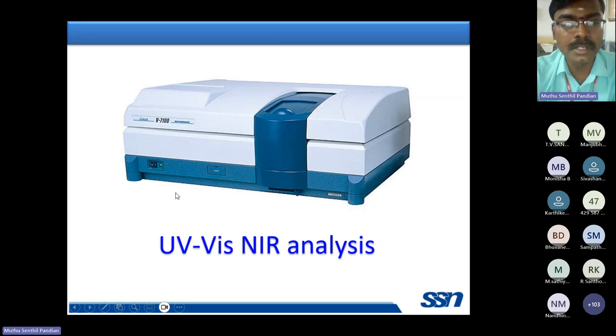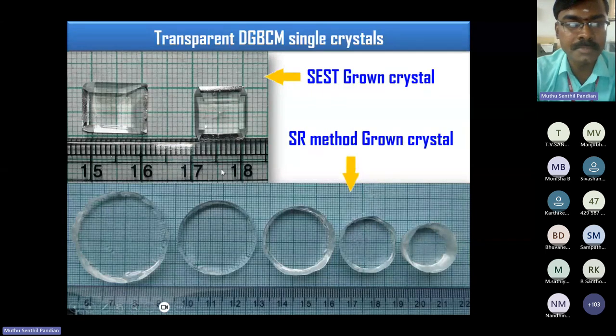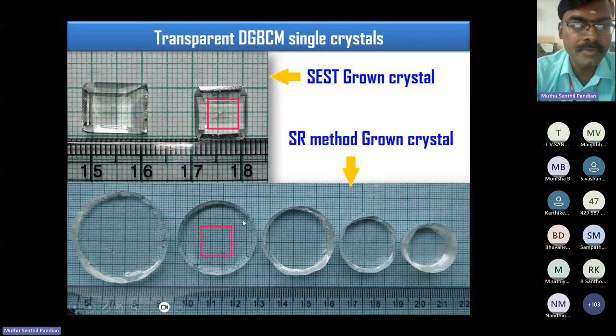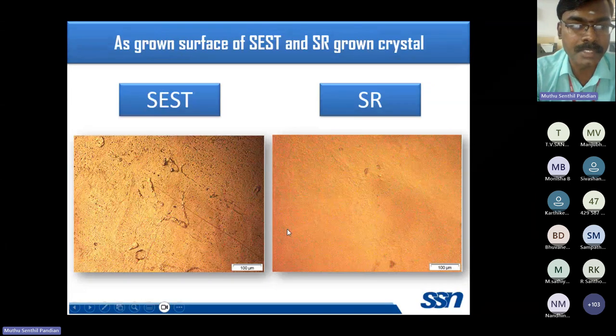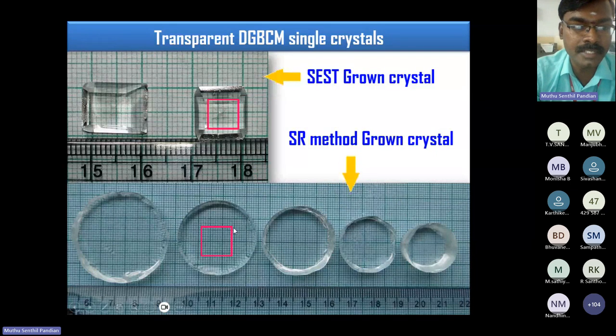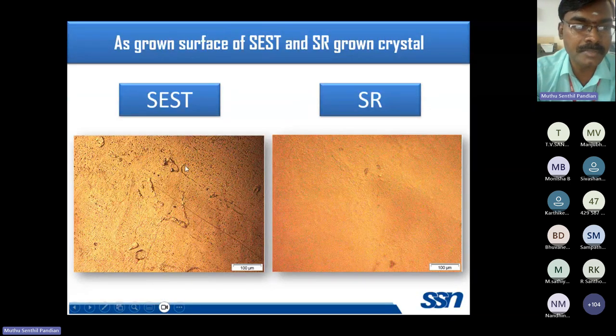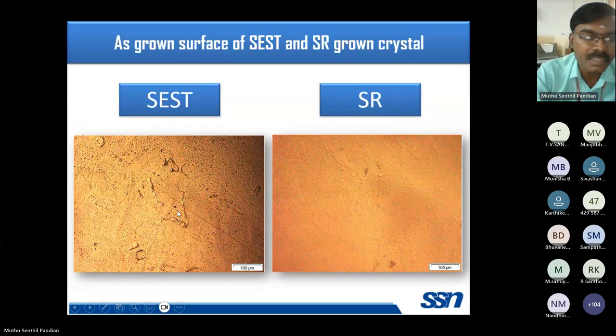To check the optical quality of the conventional and SR method grown crystals, we have performed the UV-Vis measurement. So here, we have performed the optical transmittance measurement. You see the surface, both the conventional and SR method surfaces are visibly very transparent, but the microscopic images say the conventional method grown crystal has very high roughness because of solvent inclusion, micro cracks, milky opaques, and high dislocation density.